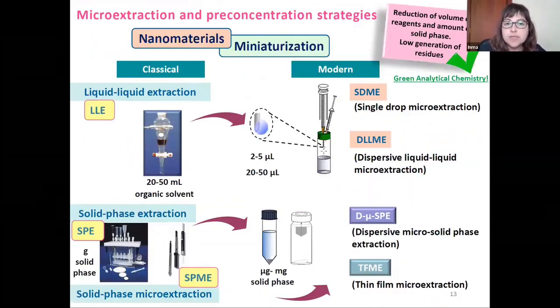In addition to using nanomaterials, the extraction and preconcentration strategies have evolved to miniaturized techniques by a drastic reduction of the organic solvent from 50 milliliters, for example, in liquid-liquid extraction, to only a few microliters, using single drop microextraction and dispersive liquid-liquid microextraction, and also by reducing the amount of solid sorbents used in solid phase extraction from grams to milligrams or micrograms, using the techniques dispersive micro solid phase extraction and thin film microextraction. It is also important to remark that low generation of waste is produced as a consequence of this miniaturization of preconcentration techniques, which fulfill the requirements of green analytical chemistry.